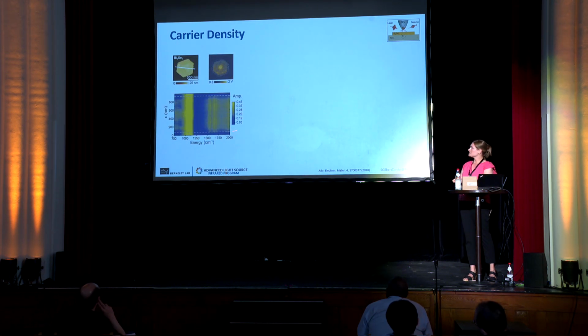So this is where the synchrotron infrared nanospectroscopy came in. So this is another topography image here where we did a hyperspectral line scan across the surface. And you can see even in this integrated image, which we call a white light image, integrated over all the frequencies we have access to, you still see this pattern of dark and bright circular regions within the crystal.